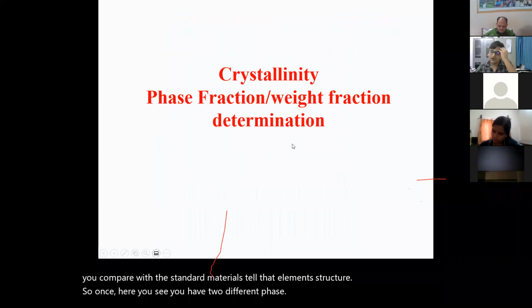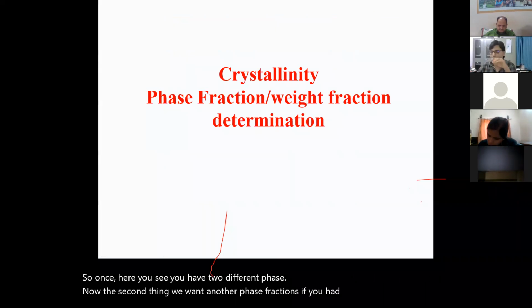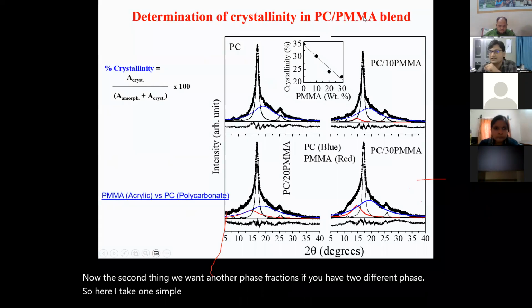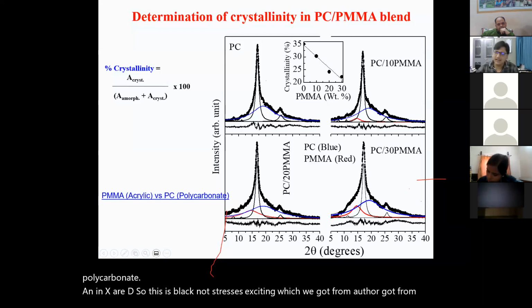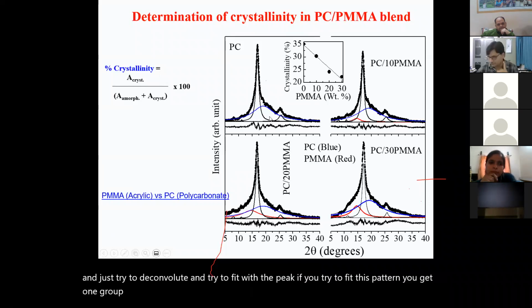Now the second thing, we want to know the phase fraction, okay, if you have 2 different phases. So here I take one simple example of polymer. Here we have 2 kinds of polymer, PC, which is polycarbonate, and PMMA, a standard famous one. And in XRD, these black dots are the XRD which the author got from the measurement. Now, without any analysis software, I think most of you are using Origin, you can just try to deconvolute and fit the peaks. So you see here, if you fit this pattern, you get one blue broad peak and 2 black sharp peaks. So this means the black is the crystalline phase, and the blue is the non-crystalline phase.